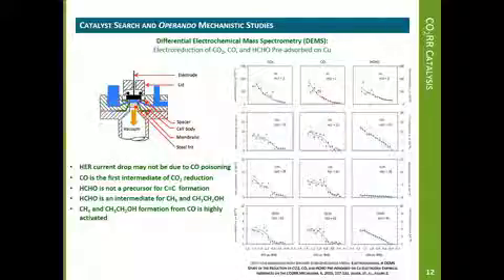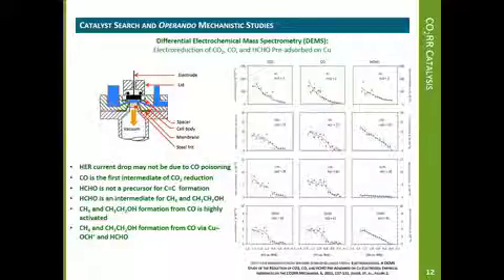For such case, two pathways are possible. One requires a theoretically postulated surface species, which consists of carbon monoxide protonated on the carbon atom, and the other involves adsorbed formaldehyde, which is formed after the rate-limiting protonation step.